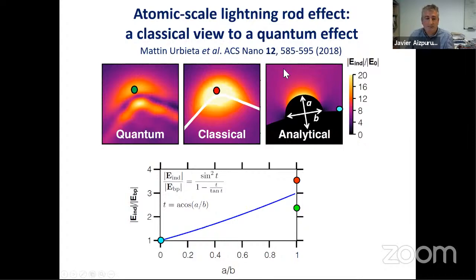But what we found recently, a couple of years ago, is that if one takes a classical solver with the dielectric functions of metal, and reproduces the sharp boundaries, classically, of the electronic density profile of your metal, you reproduce quite nicely the amplitude of the local field enhancement and the distribution of this local field enhancement around this pico cavity. So we can use in our simulations, depending on the level of sophistication you want, but in most cases, when you want to reproduce tunneling images with this level of resolution, it's enough that at the typical 20 nanometer radius tip, you add this little extra hemisphere of a few nanometers, 1 or 2 nanometers, with this kind of curvature to get this pico cavity localization and scan with that. And that works very, very well.